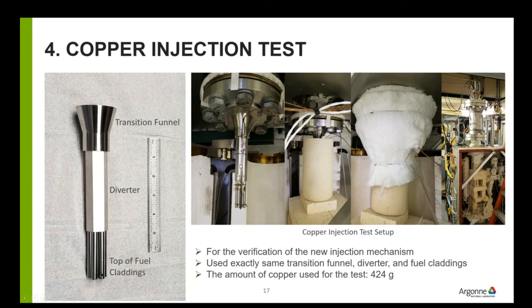This picture shows the experimental setup of the copper injection test. This is the flange and transition funnel, diverter, and cladding portion. And we put a crucible around this test setup to catch the injected copper inside the crucible. We also put insulation around it to limit the splashing of the copper out of the crucible. The amount of copper used in this test is around 424 grams, which has a similar volume to the uranium that will be used in the main experiment.